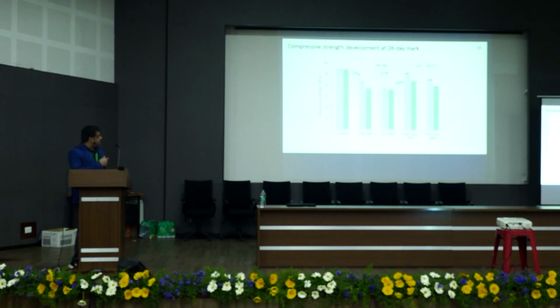Right. So in terms of 28-day strength, we saw quite a bit of improvement after carbonation, because if you look at untreated brick powder, at 25% replacement and 75% replacement of sand, there is a reduction in compressive strength by almost 20% compared to control, right? The green bar that you see here is after steam curing, and the grayish bar is after normal curing. So for both curing conditions, there is a reduction in strength. But after carbonation, for both curing conditions, we see almost 20 to 21% compressive strength improvement. That is attributed to the pozzolanic action at a later stage, because at early stage, we did not see much strength improvement.